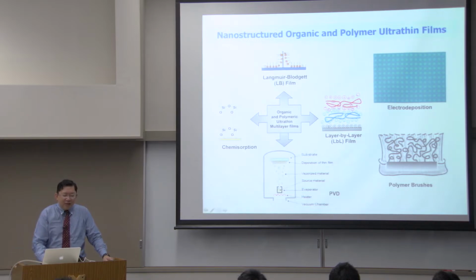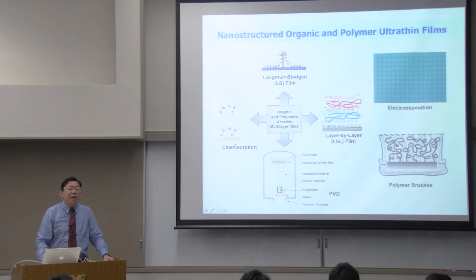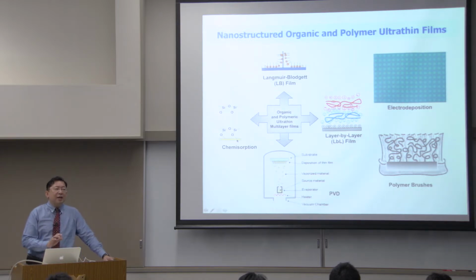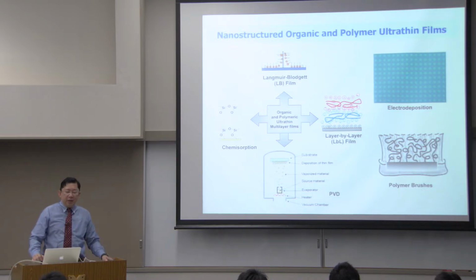One of the ways you can modify a surface is through chemistry, chemical adsorption, or chemical reaction. This can be in the form of silane coupling, self-assembled monolayers, or the use of epoxy or other reactive groups to build layers.